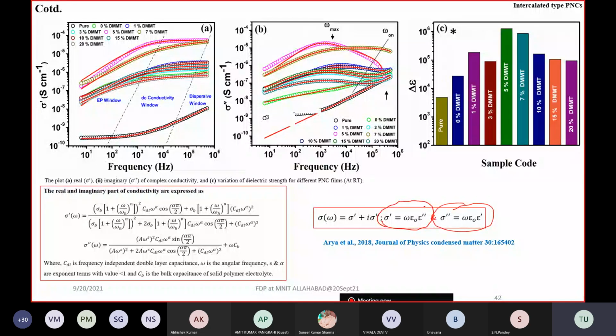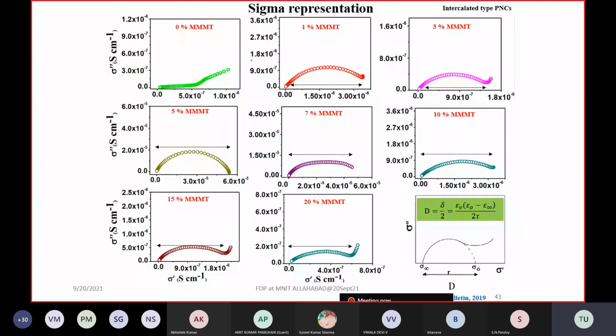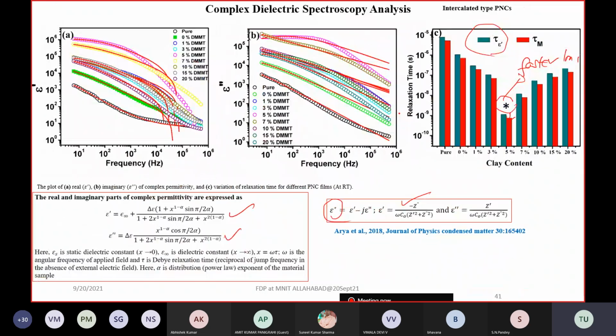Both have been plotted versus frequency here, and fitted using the theoretically derived relations, and thereafter we have come to the conclusion that the dielectric constant is maximum for the same concentration where we have maximum intercalations. And the sigma representation, sigma prime versus sigma double prime, is to be plotted in order to find out where the minimum relaxation time is, again corroborated here. Where they have the maximum diameter, there is the least relaxation time. So you see here the same 5% concentration where the intercalations occur, it is showing the least relaxation time, which corroborates what you found earlier in this analysis.